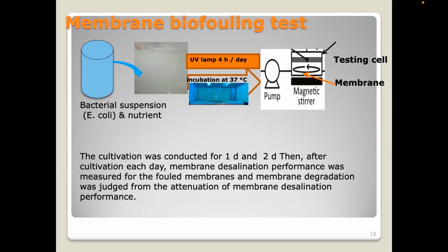And then every day we test the membrane for desalination and for foulant. From this experiment, the cultivation was conducted for 2 days. After cultivation, each day, membrane desalination performance was measured for the fouled membrane, and the membrane degradation was judged by attenuation of membrane desalination performance. We found a good result for preventing biofouling on the membrane.